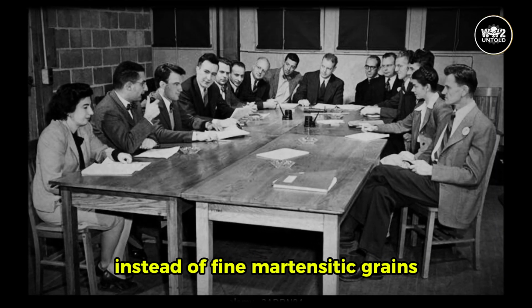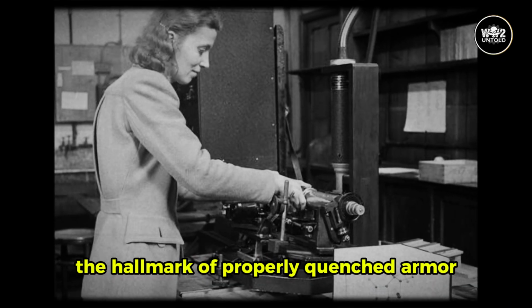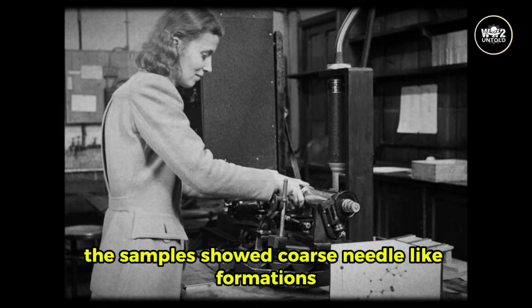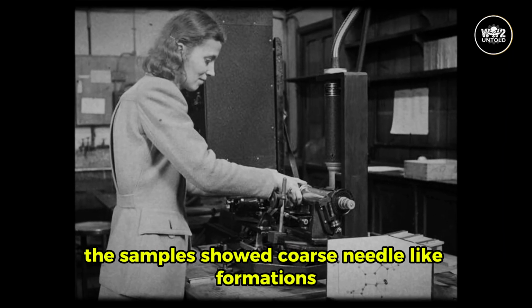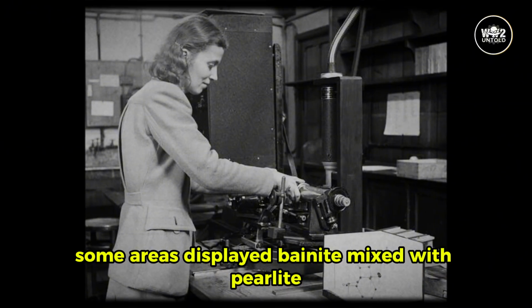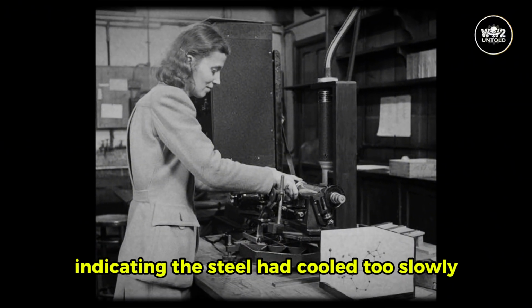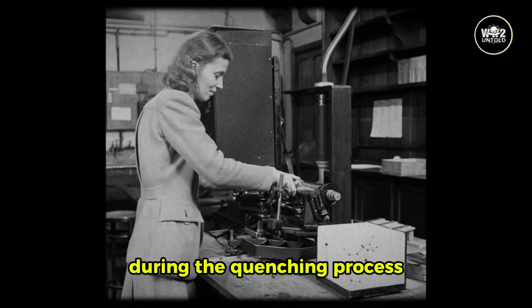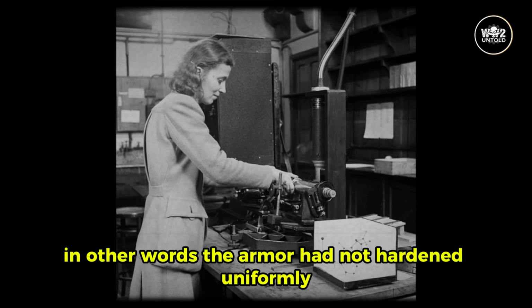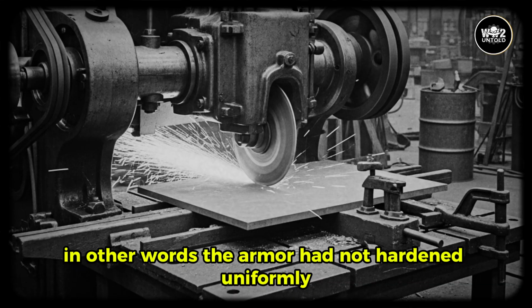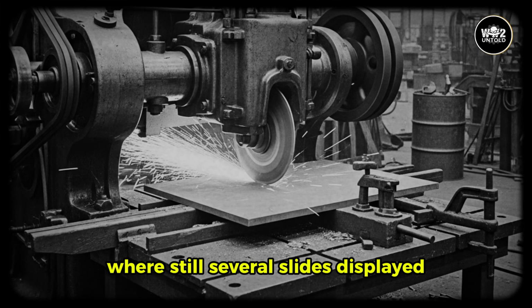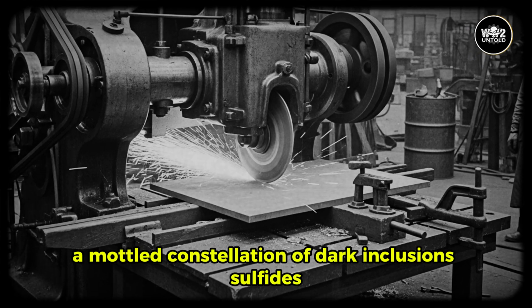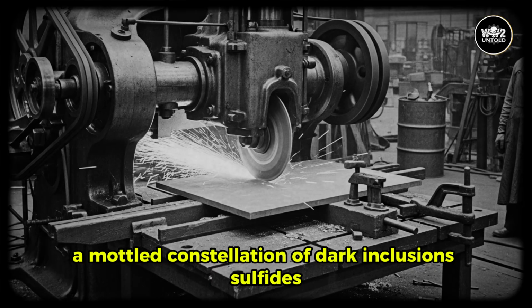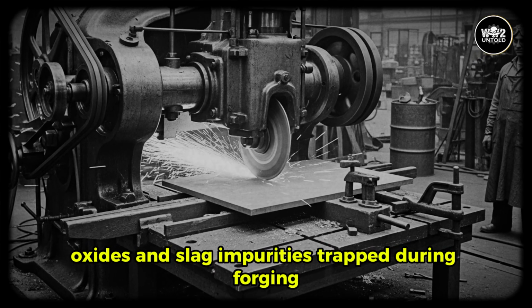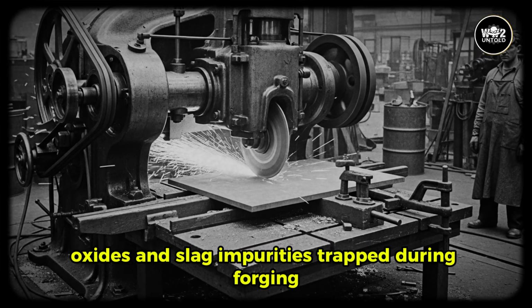Instead of fine martensitic grains, the hallmark of properly quenched armor, the samples showed coarse needle-like formations. Some areas displayed bainite mixed with pearlite, indicating the steel had cooled too slowly during the quenching process. In other words, the armor had not hardened uniformly. Worse still, several slides displayed a mottled constellation of dark inclusions, sulfides, oxides, and slag impurities trapped during forging.